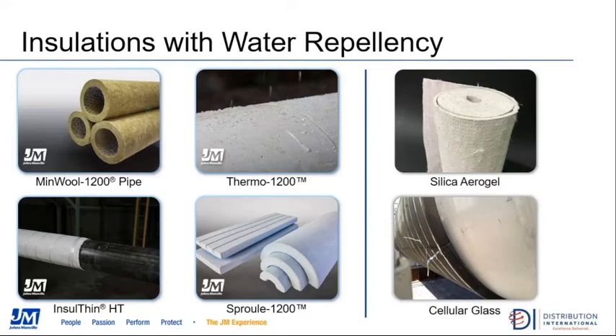In addition to these products, the silica aerogel thin blanket insulation products are treated such that they are water repellent, hydrophobic, and cellular glass insulation, which is typically considered to be a zero perm material, would therefore naturally be water repellent or hydrophobic as well.